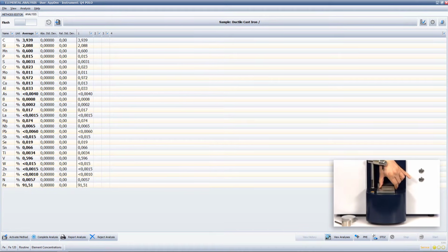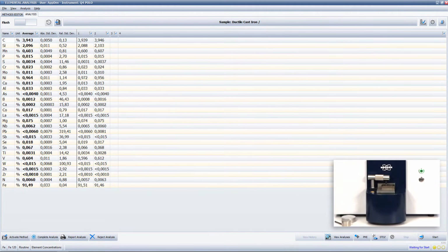Ductile cast iron is also called nodular cast iron because carbon forms graphite in the form of small nodules, which makes the quantitative carbon analysis more difficult as the carbon distribution in the material is not homogeneous. But as you can already see on the analysis screen, this is not an issue for the Q4 POLO at all, and it can precisely analyze the carbon together with other main alloying elements such as silicon, manganese, nickel, magnesium, chromium, and phosphorus in cast iron.